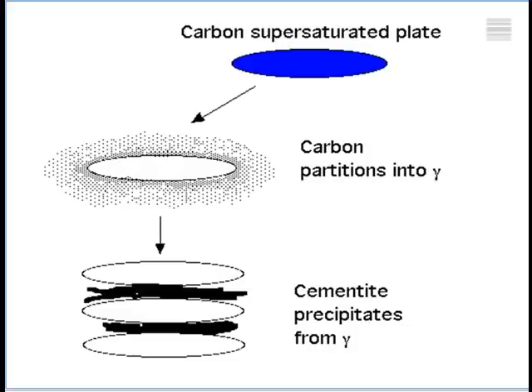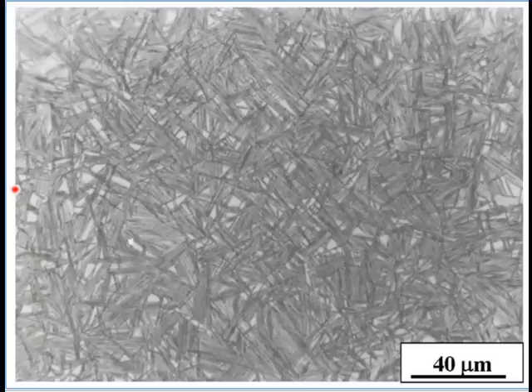What we are doing is we have a low average carbon concentration, but the carbon is redistributed into the austenite and it stabilizes the austenite. So you produce a nice microstructure which has only two phases, both of which are ductile, the bainitic ferrite and carbon-enriched retained austenite. If I show you an optical micrograph of that, where you see bainite in all kinds of directions, the white regions there, the light etching regions, are the retained austenite.